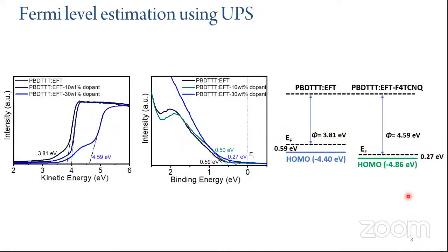And further, the UPS spectra was also studied, where the work function of the pristine polymer is at 3.81 electron volt, and upon increasing the dopant concentration, it is increased to 4.59 electron volt. So this increase in work function also confirms that the doping is shifting the Fermi energy level to the HOMO.